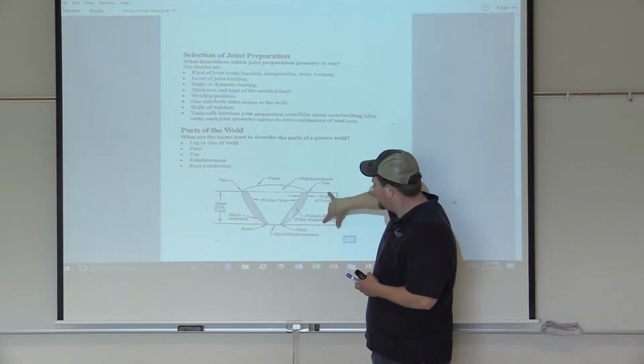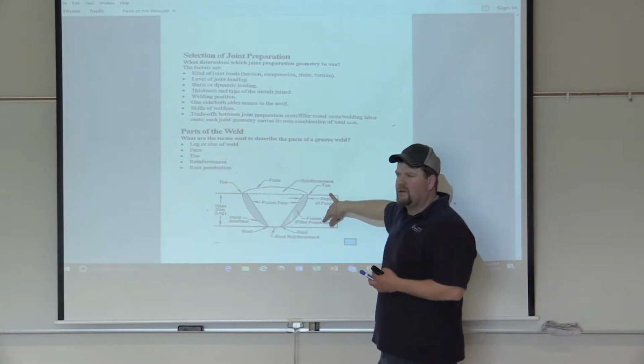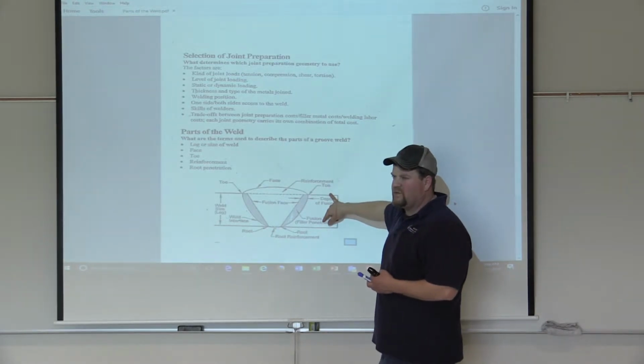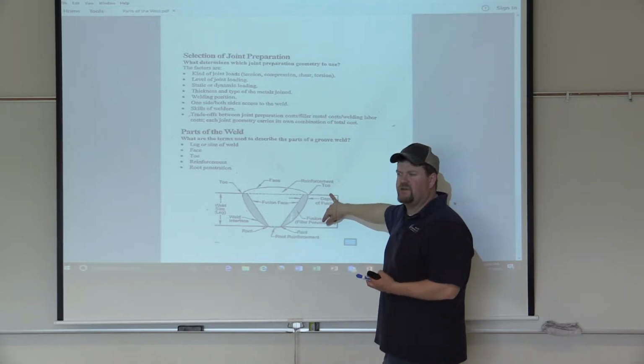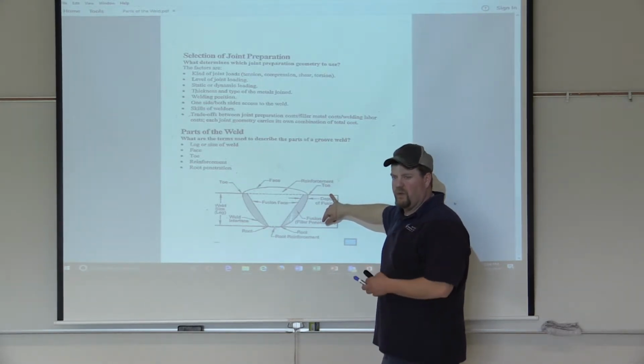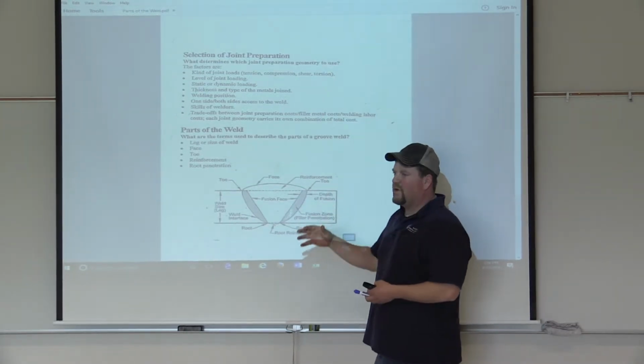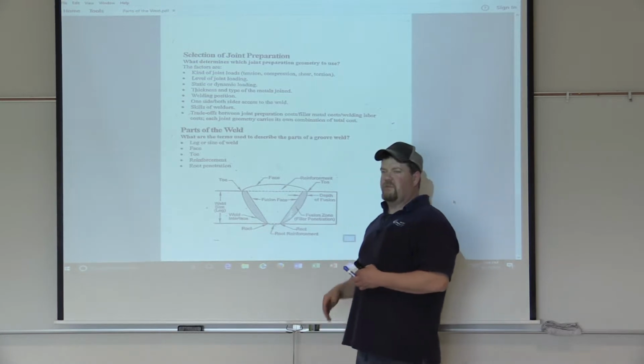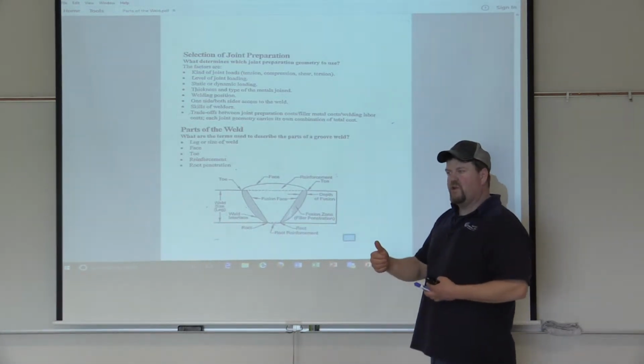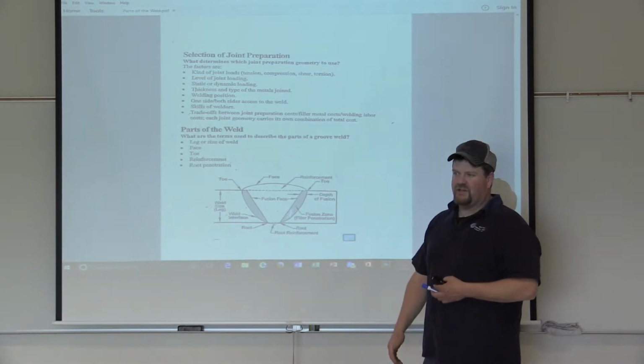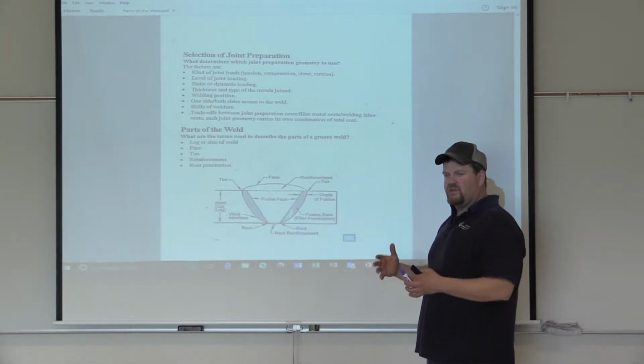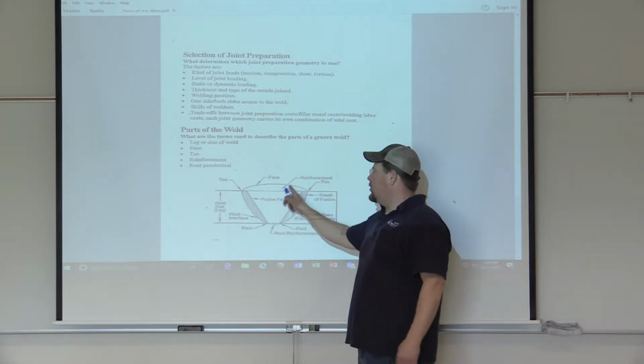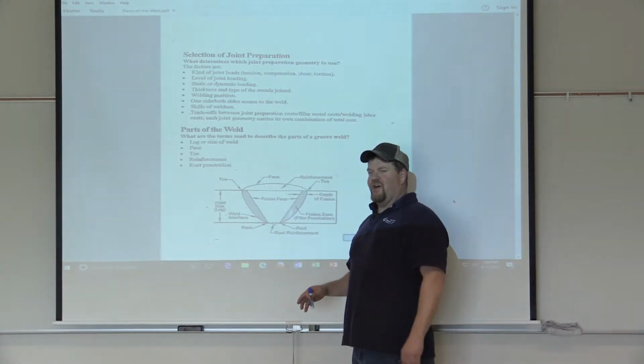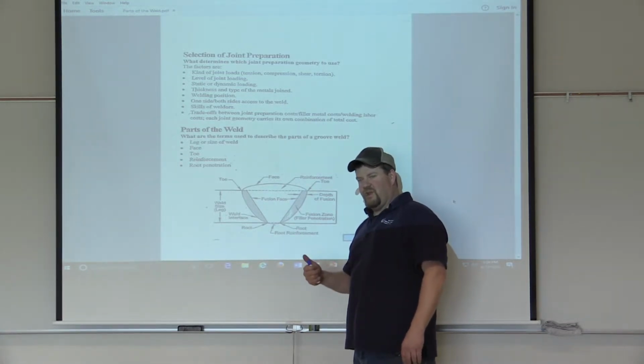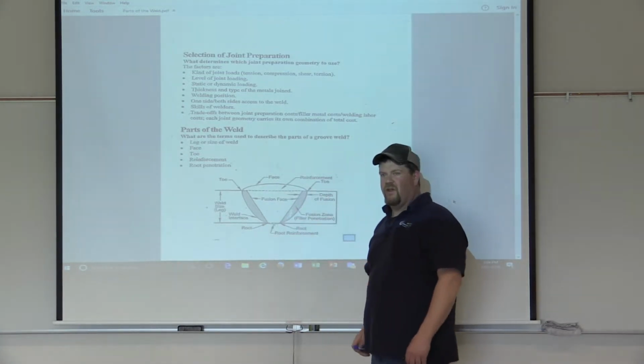So if this is 1 inch thick plate, what's the maximum size of this weld? 1 inch. Even if it's got an 1/8 inch reinforcement, still a 1 inch weld, okay? And actually in AWS code, you're allowed up to 3/16 on 1 inch, but it's still called a 1 inch weld, right? So when you see on the print 1 inch weld, and you see that it's prepped as a 1 inch weld, you know it's complete joint penetration, but you're also allowed 3/16 of an inch leniency. So see how knowing these codes helps you as a welder say, oh, I can go quite a bit more. I don't want to take a chance of getting undercut. 64th of undercut will put me down the road. But if I'm 1/8 of an inch above, I'll be fine all day long. Okay?